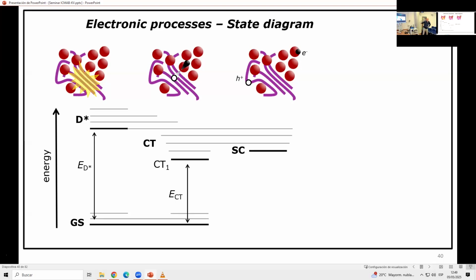This is what happens in an organic solar cell. This is energetically then, I try to draw. First you shine light, and if it's a polymer blended with an acceptor or something, this is how I imagine it. You excite the polymer. This excitation goes to the interface or is already close to the interface and is transformed to a pair, an electron-hole pair, which is at the interface. But you're not there yet because the electron can still fall into the hole here. That's then this charge transfer state, which you can go down here. You can lose it, or you can excite it directly, but the absorption was very weak.